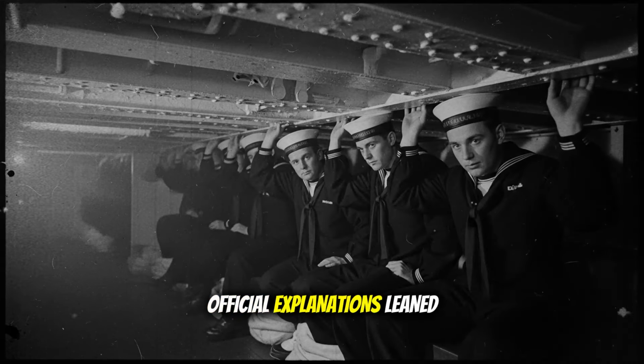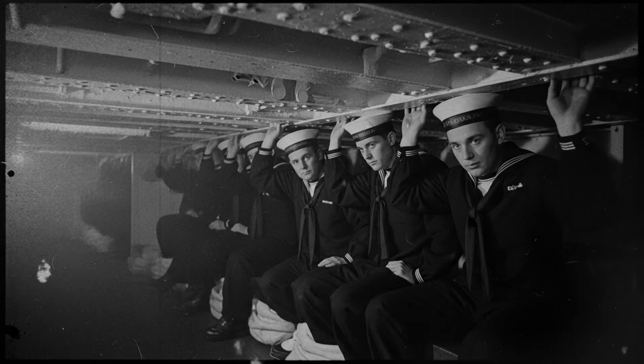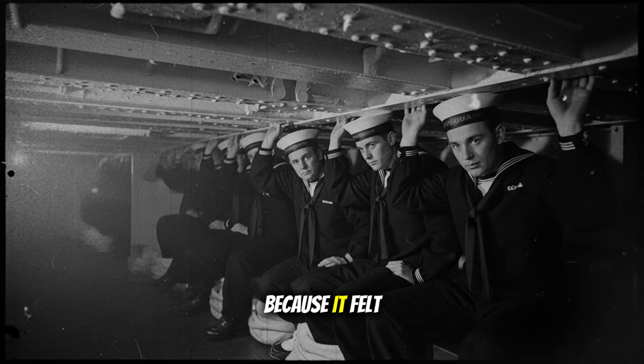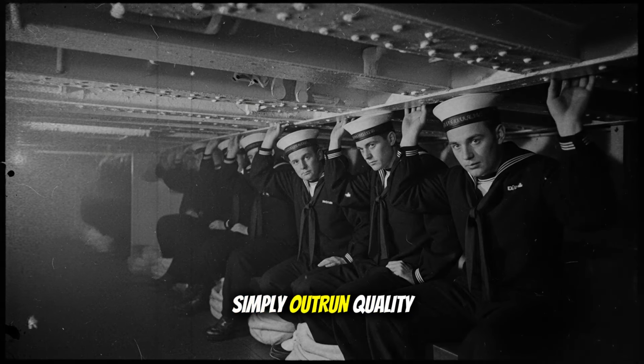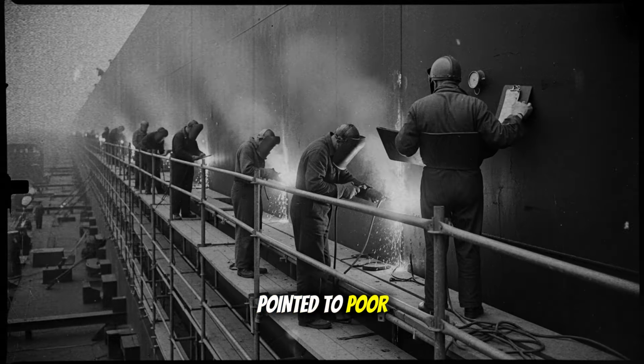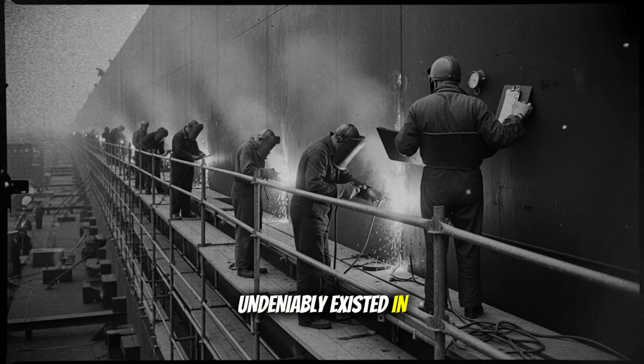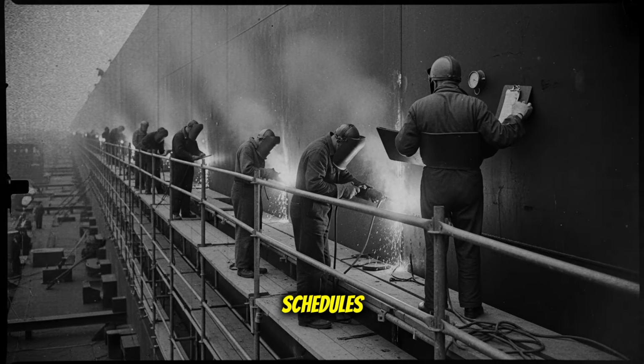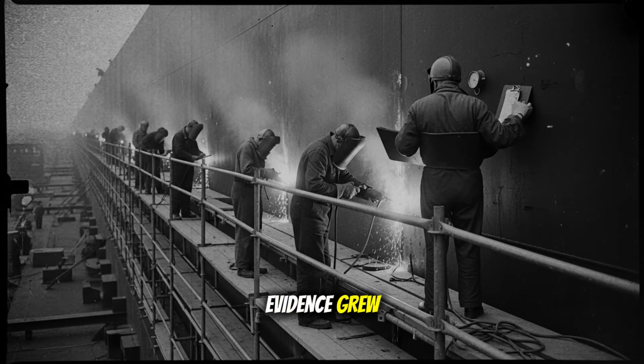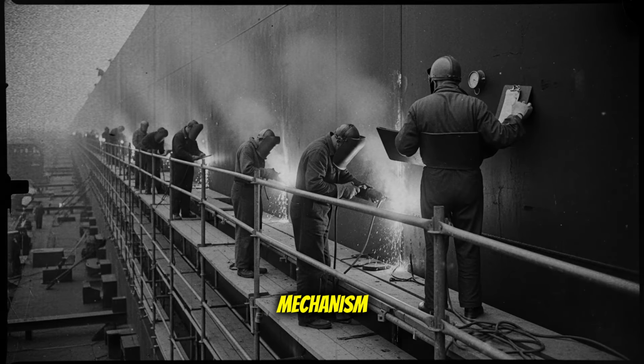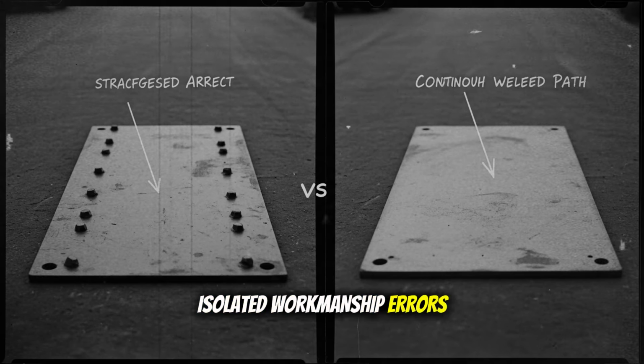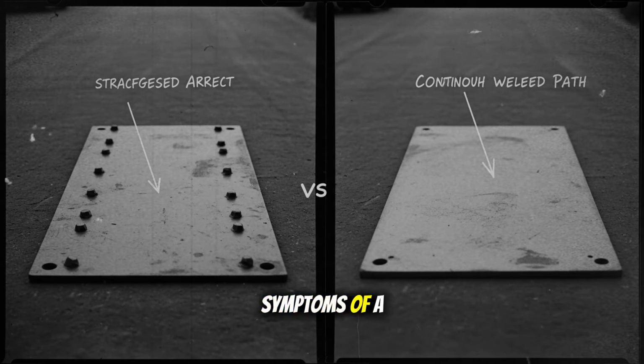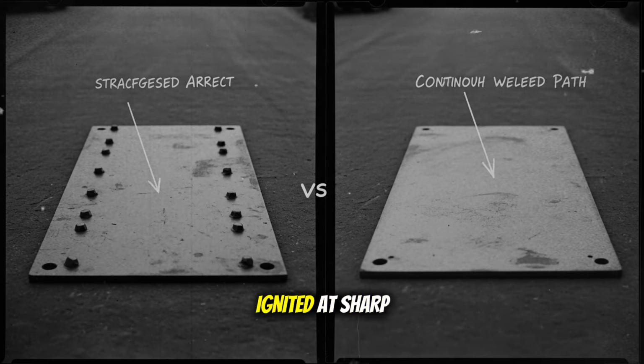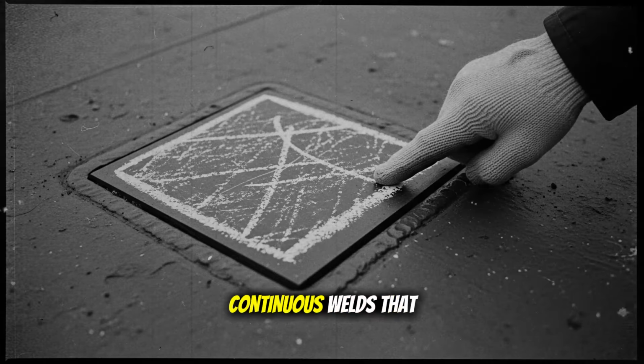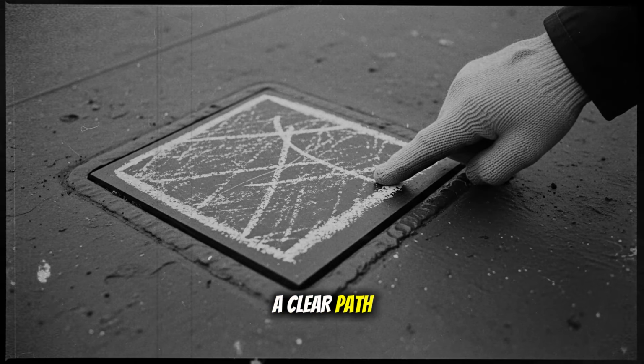The first official explanations leaned on familiar culprits: faulty welding and rushed work, because it felt intuitive that speed had simply outrun quality, and early reports pointed to poor practices that undeniably existed in some yards under punishing wartime schedules. But as the evidence grew, the narrative shifted from blame to mechanism. What looked like isolated workmanship errors were, in many cases, symptoms of a deeper physics: the brittle fracture of low-toughness steel at low temperature, ignited at sharp corners and accelerated by continuous welds that handed a crack a clear path.